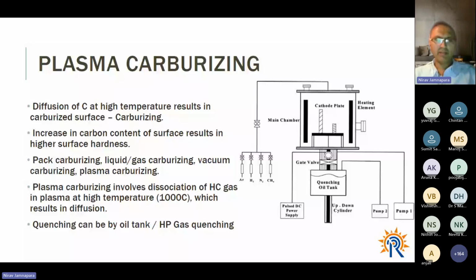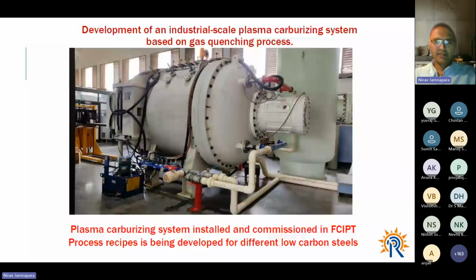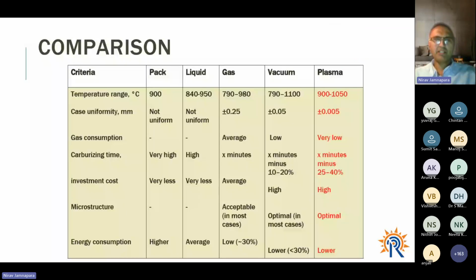Quenching can be done in an oil tank, but high pressure gas quenching is the most recent advance, and today oil quenching is not considered the gold standard for the heat treatment industry. High pressure gas quenching gives tailored results and is the most desired by the industry. As you can see here, there's a large, industrial scale plasma carburizing system based on the gas quenching process. This was recently installed at FCIPT, and we intend to develop the process for different kinds of low carbon steels.